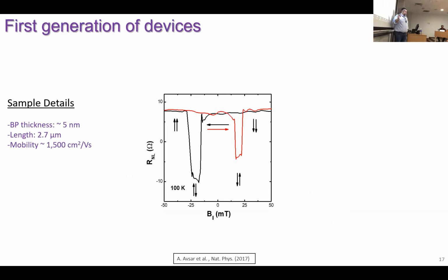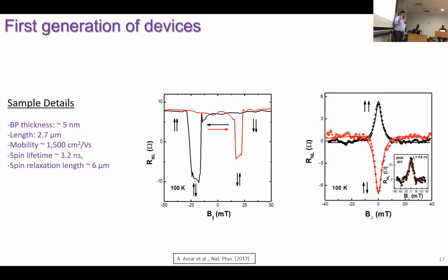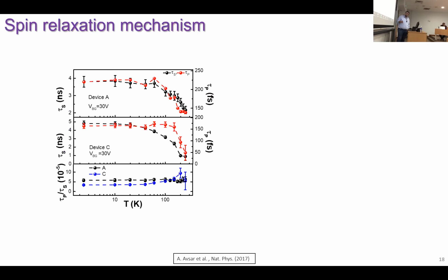And we started to measure the spin transport in this material. So we were not extremely hopeful. But indeed, we started measuring immediately at low temperatures, and we could see a clear spin transport signal. And then we also saw quite nice spin Hanle measurements in this black phosphorus channel material, and the spin relaxation times that we extracted were around 3.2 nanoseconds, which was much better than any graphene-based device that we have measured. So the spin transport properties of this material were quite nice.